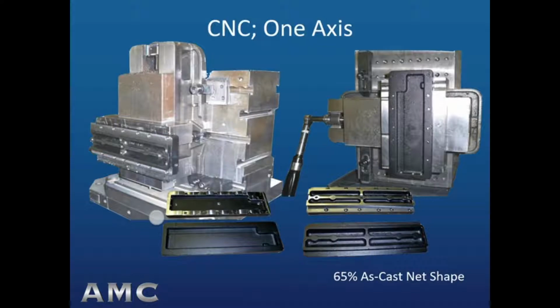The casting has a drafted surface around the entire perimeter of its rectangular shape. Normally, it's good practice not to fixture on drafted surfaces. However, if it is done carefully with an understanding of how draft works, setting up on draft can be successful as it is shown here, realizing that the draft is really a combination of an offset and a draw length, like the offset and depth of a cupcake pan.